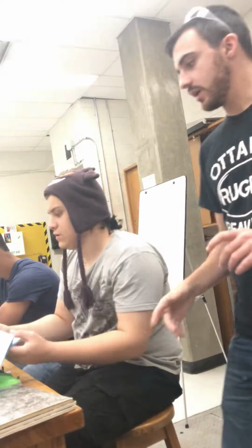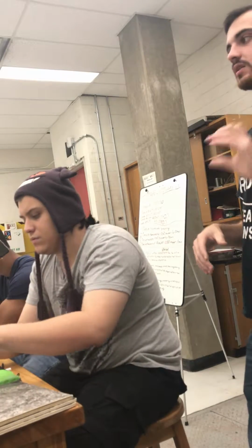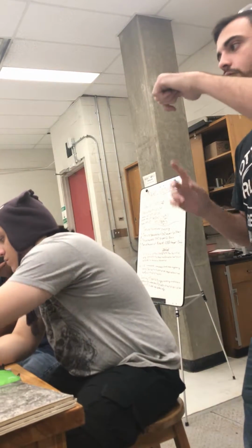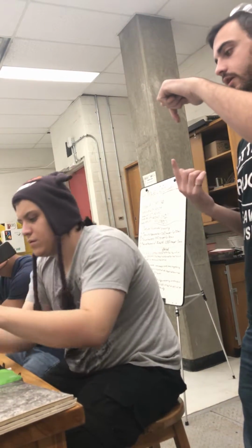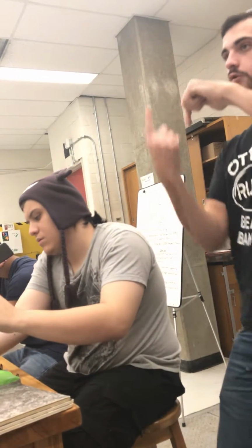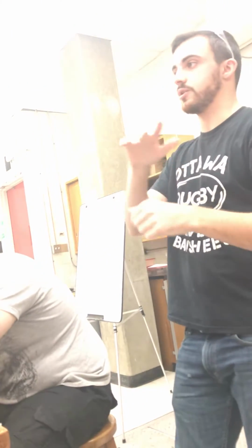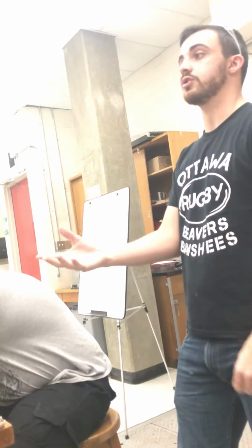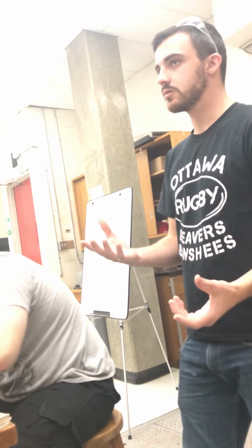Yeah, so as your martensite's breaking down, it's decreasing your hardness. You have a formation of your alloying carbides, which increases your hardness, so the net effect is a zero change or a minimal change in hardness. Does that make sense? Minimal change.